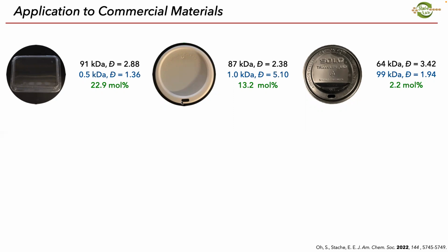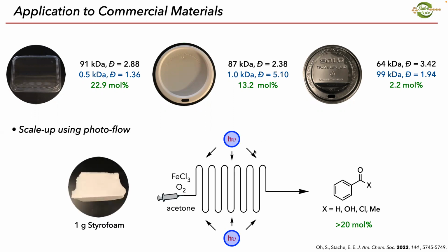But one of the challenges we face in plastics recycling is that a lot of the materials we make are not pure polymer. They're not pure plastic. They have dyes, they have composite material, they're mixed polymers. And so this is what we see here in this coffee cup lid that we have. There's white dye in there, there's composite material that doesn't break down. And in the case of this black coffee cup lid, which I'm pretty sure is entirely cosmetic, that black dye inhibits light penetration into the system. And so now we can't break it down for that reason. So we have to find a way to remove that dye to improve our process. So this is just to illustrate the challenges that we face in plastics recycling.